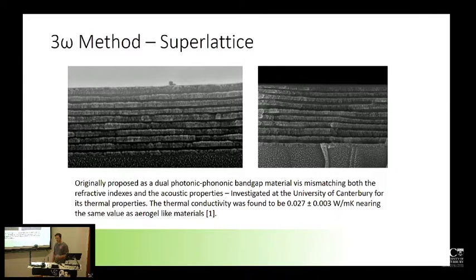Honestly, that was kind of surprising to me, at least, mostly because the whole premise of this was that we were going to get multiple coherent thermal waves crossing over boundaries and reflecting off these surfaces and acting like a thermal mirror. That was the theory, at least. But the mean-free path of phonons in PMMA and amorphous silica at room temperature is on the order of half a nanometer. So the idea that we would have thermal waves crossing all of these boundaries and reflecting seems far-fetched, to say the least.